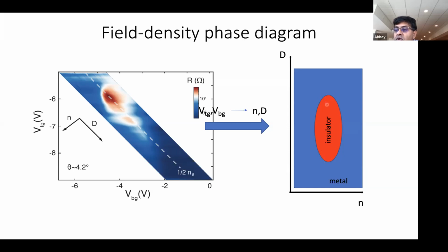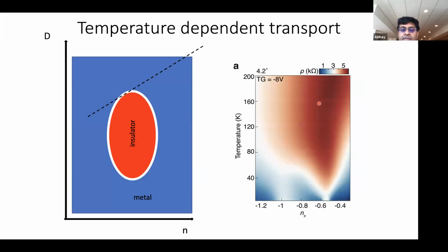And one can ask, what does the transport behavior of a sample like this do as you sit at various points in this phase diagram and vary the temperature? And what we've discovered is that it's quite interesting, and I've been talking quite a bit with Chimiao as well about this. So let me show you some transport data which is taken along this particular line. It's a line of almost constant electric field, not exactly constant electric field, and it's sort of intersecting the region where the insulating phase is exactly the boundary.